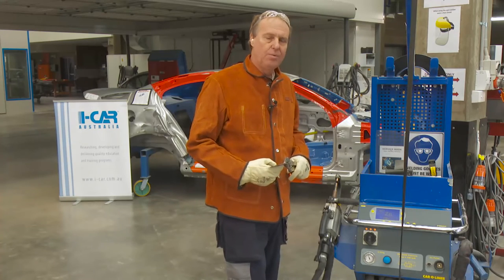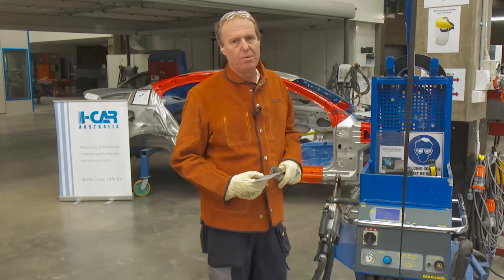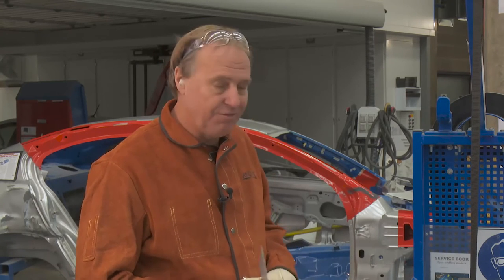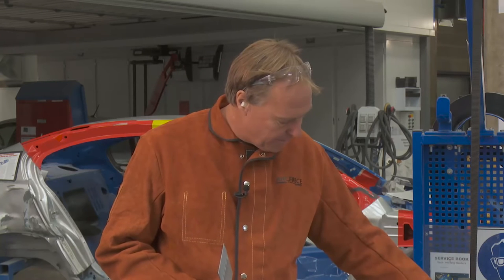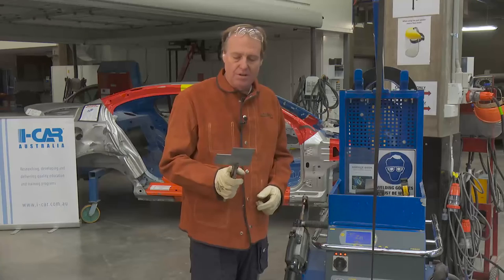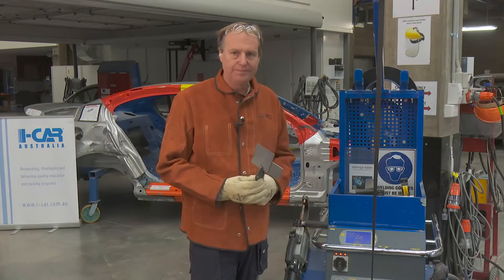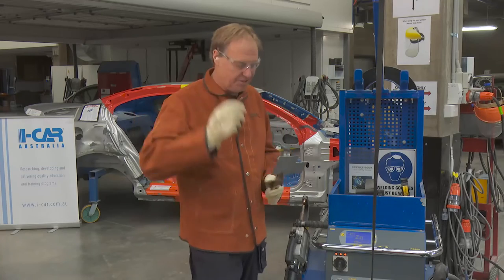Okay, we've just stepped out of the actual welding bays where we were doing fusion welding. This is actually a spot welding, which is known as squeeze type resistance spot welding. A different process to actual MIG, or otherwise known as mag welding for plug welding. Spot welding works on resistance more so than a fusion through a weld puddle. If a procedure calls for spot welding, we need to fully understand the settings that need to be programmed as far as steel type, coating types, and metal thicknesses. So I'll do a demo on these two plates that we have here and see the result.